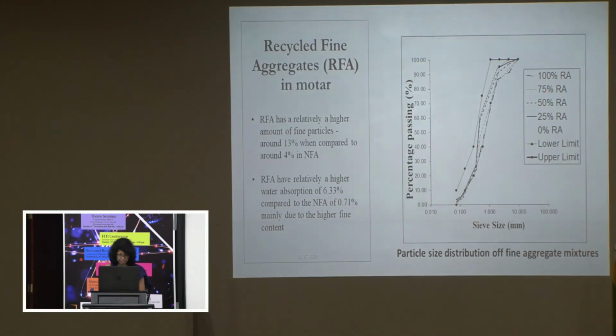We have looked at the use of recycled aggregates manufactured from construction waste as an alternative for fine aggregates in bedding mortar. It was seen that all the fine aggregate mixes we tested were mostly within the standard envelope accepted for fine aggregates to be used in bedding mortar applications.